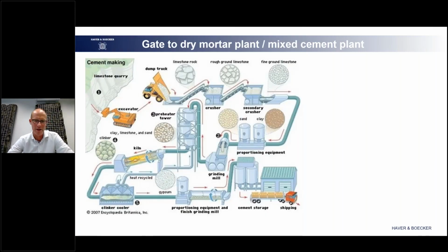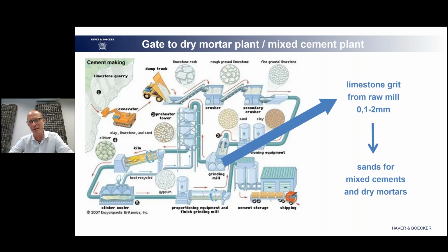Again, we are here in our chart, and today we have another split point, because to receive the ingredients for dry mortars and mixed cement, we need, of course, the binders, the cement here in this field, which we have already in our final silos, but also to create the typical sands we need for it. Here we can just go into the raw grinding mill, and here we extract material which is minus 2 millimeters, for example. And there we have the link, the exit, to create these mortar sands. How does that work?